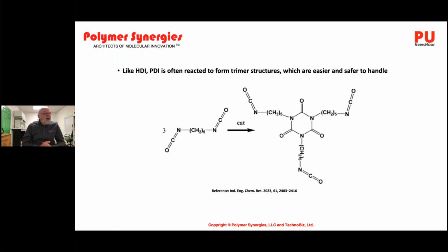Like HDI, PDI is often reacted to form these trimer structures. And the reason this is done is to make these materials easier to handle. It also creates a trifunctional molecule rather than a difunctional molecule. But because the molecular weight has increased, these materials are much safer to handle and easier to use. So just like HDI is often sold as the trimer structure, so can the PDI.